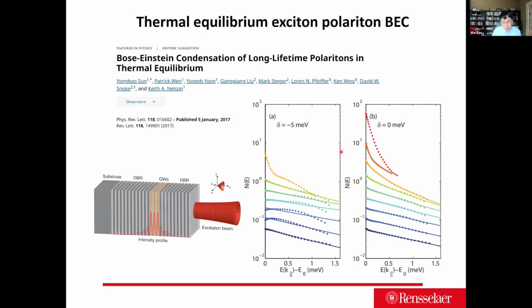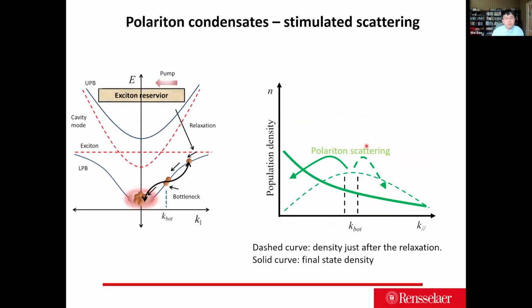Later on, people in the community also showed that if you make the quantum well structure with the growth of the DBR over a very long time, you get rid of the stress residing in each DBR layer from faster growth. You tune the growth parameters and make everything a really, really slow growth. Then the Q factor of the system can become really high, which means you really trap the photon in the cavity for a long time, and the exciton-polariton hybridized system has a really long lifetime. With such a system, you can even see they truly go to thermal equilibrium Bose-Einstein condensate, with all the occupancy precisely following the BEC dispersion curve. So the system does work with quantum wells, in summary.